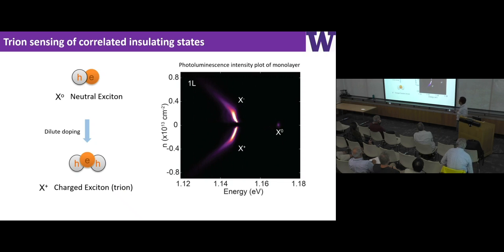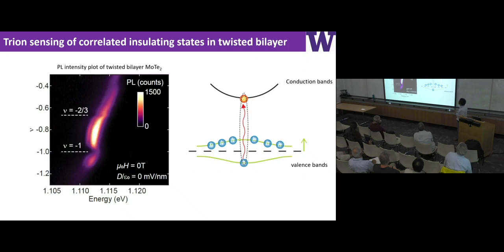Now, what I show you here is a trion intensity plot as a function of doping, which I already converted to filling factors, but for twisted bilayer MoTe2. In this plot, you will see there are two kinks in terms of filling factor. The first kink points to the -2/3 filling factor. The second points to -1. At these two kinks, you see the trion luminescence actually drops.